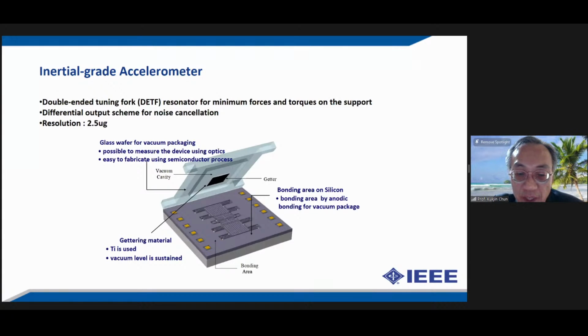And for this one, you have a resonant type, oscillating type, the beams. And then if any acceleration is applied, then they change the frequency of the oscillation. So it provides a digital output directly from the sensor. And it's vacuum packaged because there is a moving part. So it has a silicon wafer at the bottom, and on the top is the glass wafer anodically bonded. And then in the vacuum environment, as the time goes by, the outgassing of some materials can happen. So this vacuum package has a getter material, which is titanium in this case. So it lasts quite a long time.